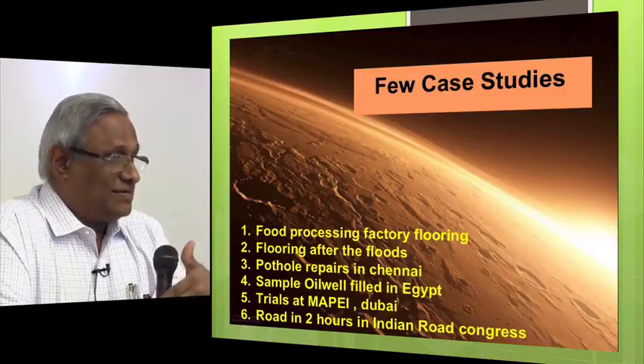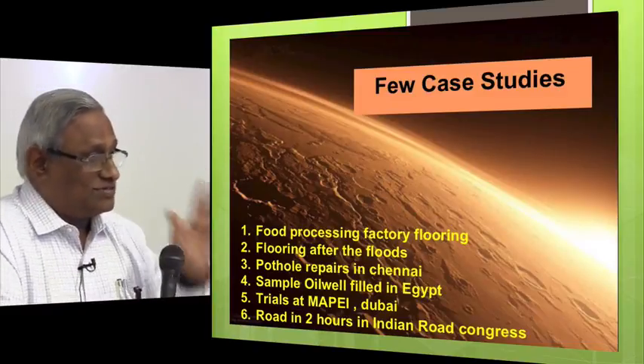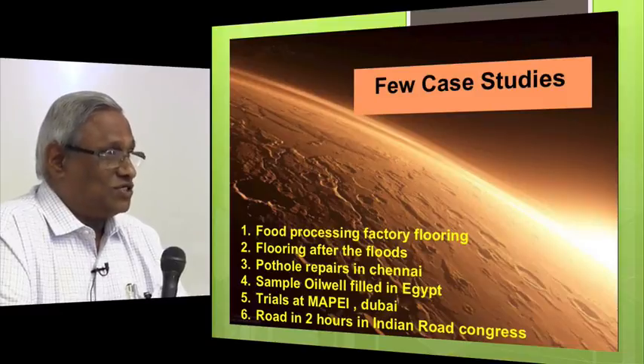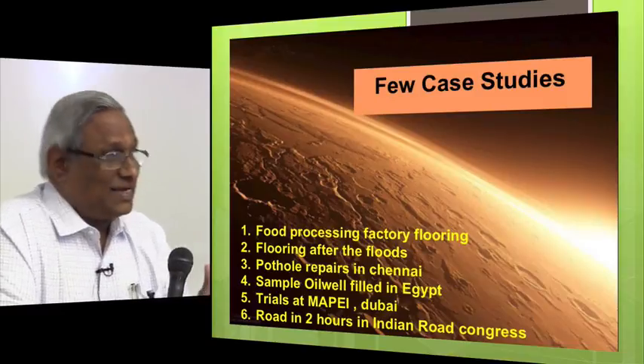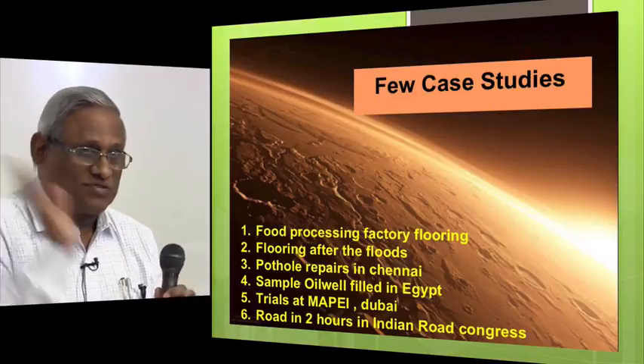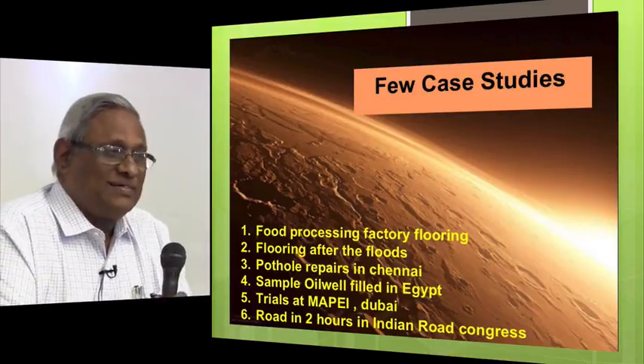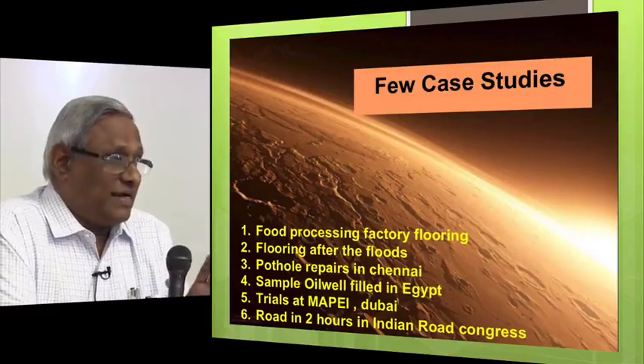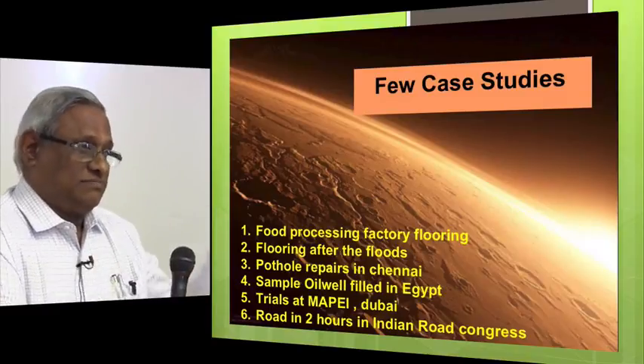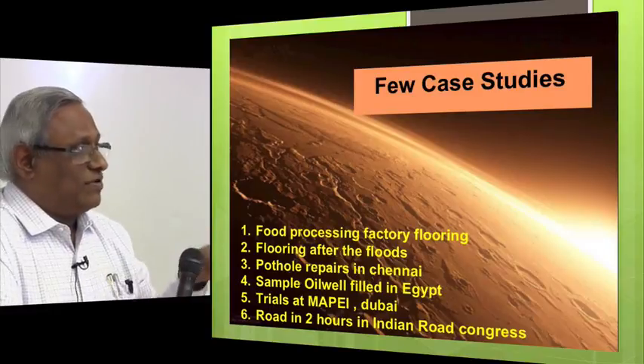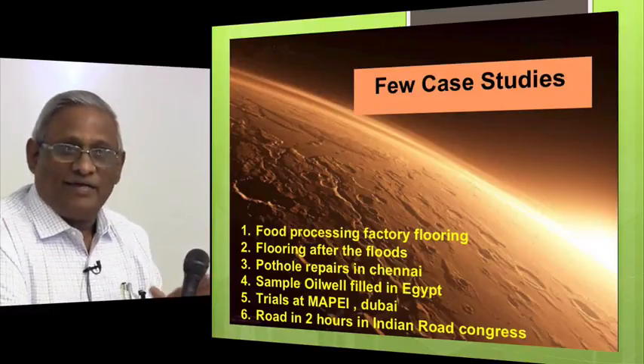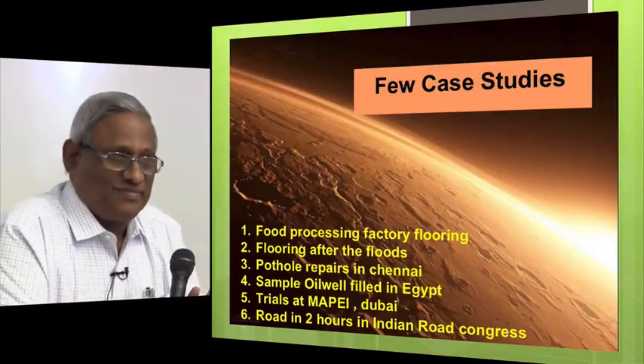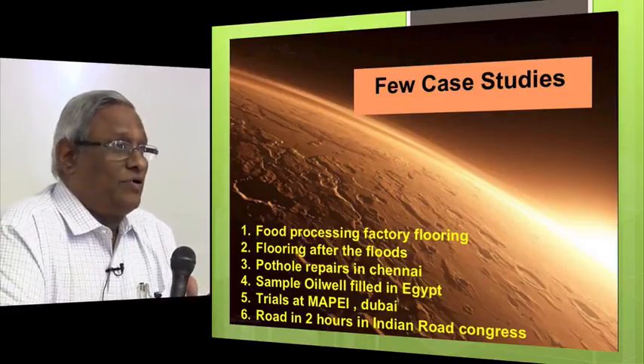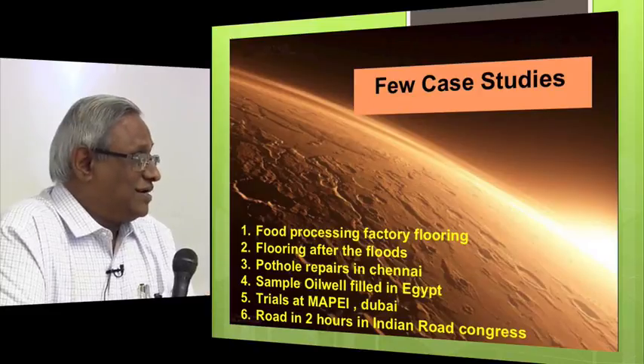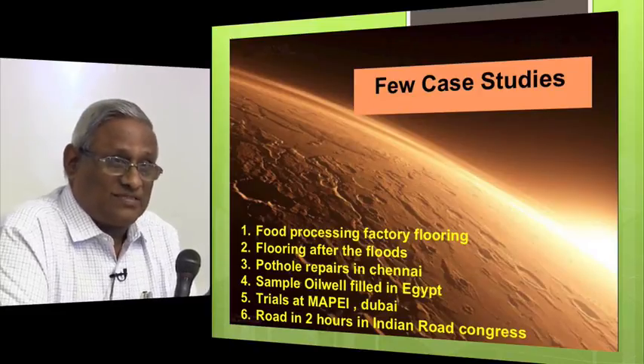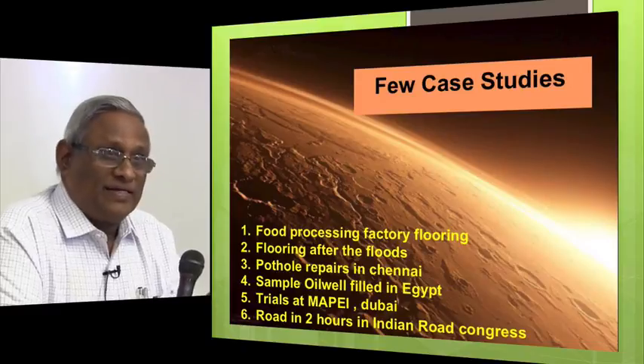And after an hour, we asked everybody to move, walk around, and they walked around, and there were no shoe marks, nothing. And actually, after 4 or 5 batches, they removed all their gloves because it was absolutely harmless, and they enjoyed it. After 3 hours, we started laying the tiles. The entire 1200 square feet of tiles was laid in about 4 hours, and the house was ready overnight for use. This is a very important thing, whereas if you use a normal thing, I think you're going to wait for weeks. The house that we made is my own house.